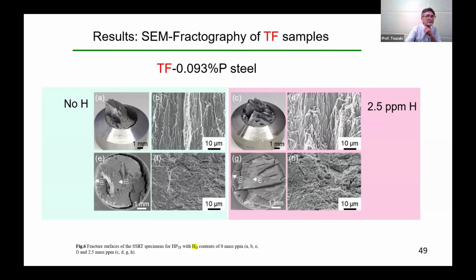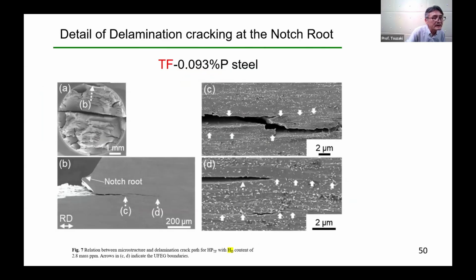This is the result of SEM fractography of TF 0.093% P steel. Interestingly, delamination was observed even without hydrogen charge, as shown in A. Delamination was then accelerated by hydrogen charge, as shown in C and D. This shows the detail of a delamination cracking at the notch root. The portion shown by B in A was cut vertically and observed by SEM like this. It can be clearly seen in B. Here is a notch root.